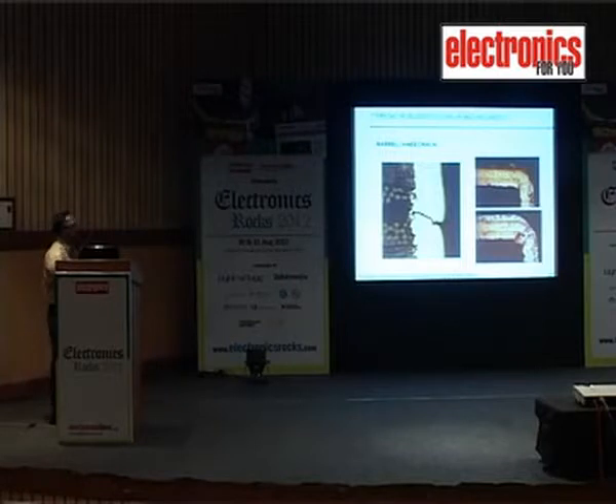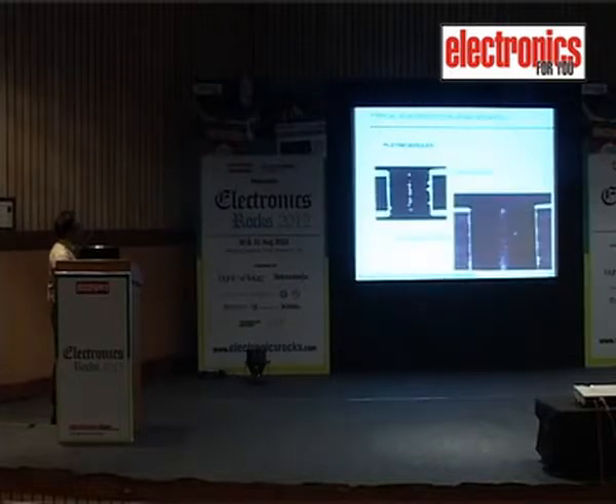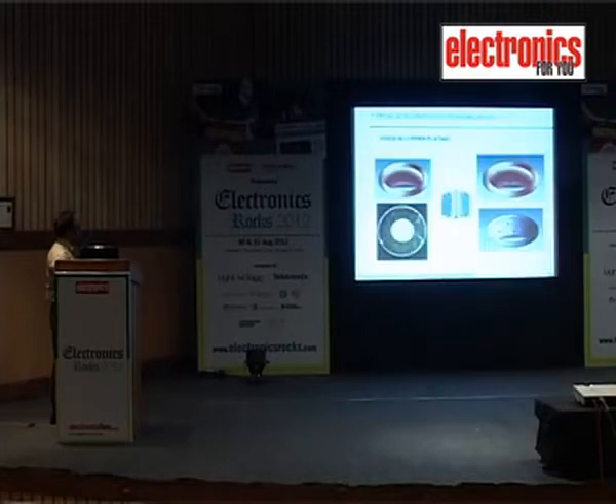It should have good elongation properties, which will be measured during the qualification cycle. And the plating nodules are also not acceptable because they can hinder the insertion of the leads. When you are inserting the lead, these nodules can be dislodged by breaking this hole wall barrel and thus affecting the quality. And thin copper, insufficient copper thickness, also can lead to the failure of the PCBs. And voids in the copper plating are one of the major defects which we have to avoid. Voids on the pads, all this amounts to rejection of the PCBs.